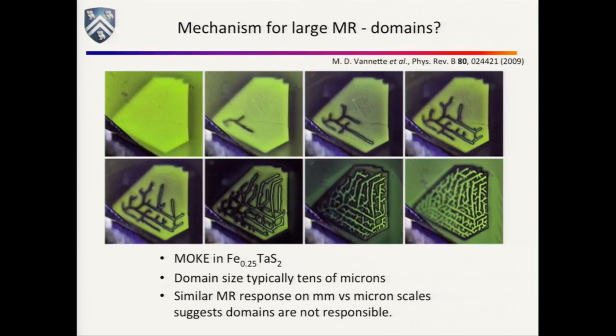It's interesting to note we have not done magneto-optics at a bunch of different concentrations, but generically at a quarter and a third, people have done magneto-optics, and what you find is that the domain size, so this is like a millimeter, right? So the domain size is kind of tens of microns, 10 microns, right? So the fact that you actually see the same magnetoresistive response in few micron samples as you do in millimeter samples tells you that if you were seeing effects due to individual domains, you'd expect to see some kind of discrete switching, and you don't see that at all. So it seems like this has something intrinsic in the material, at least on very small scales, not macroscopic domains. So what do we think is going on?